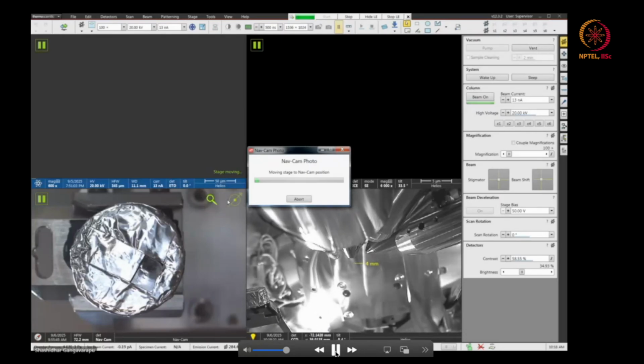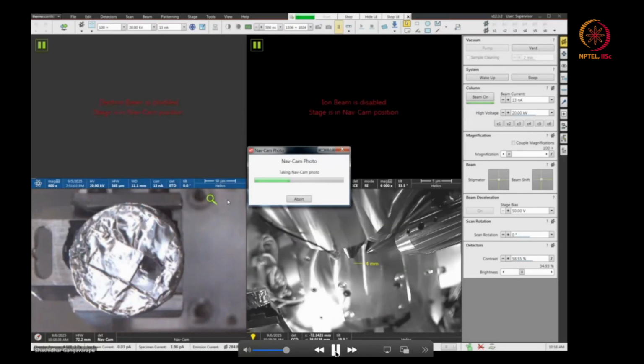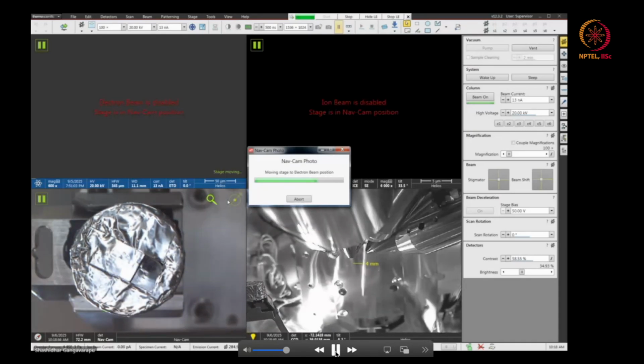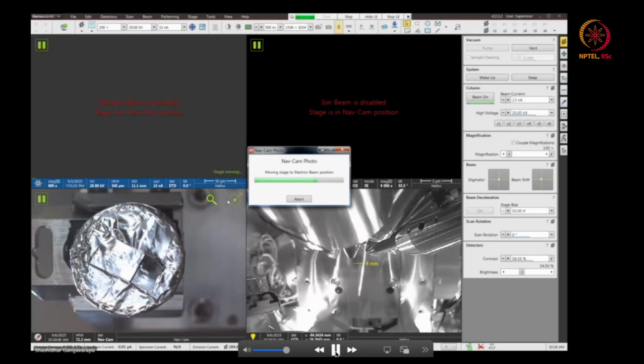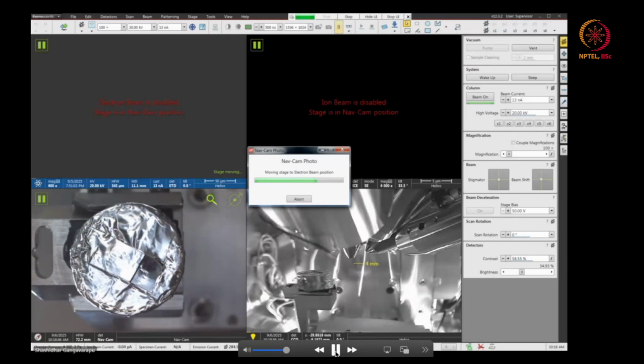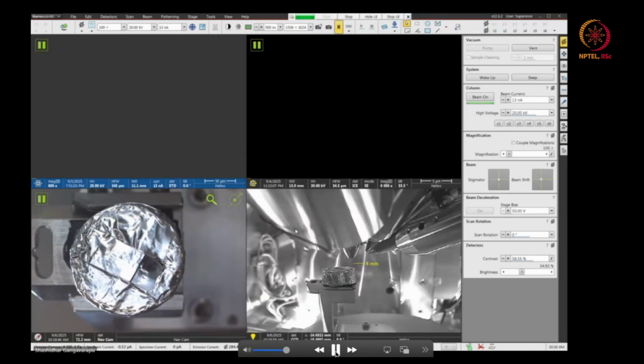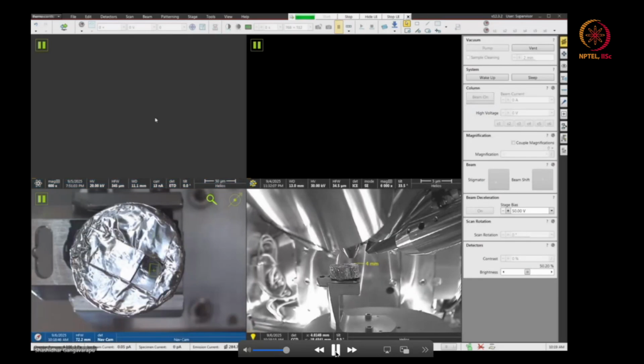Now I am doing the NavCam. NavCam is taking the picture of our sample. So now it's taking a photo of our sample, and it will take at least 10 to 15 seconds to take the picture. Now you can see that it has already been taken, and the next step is to double click on my sample. You can see my sample is wrapped with aluminum foil. Now I double click it, and once I double click, my sample is perfectly aligned with respect to the electron beam.